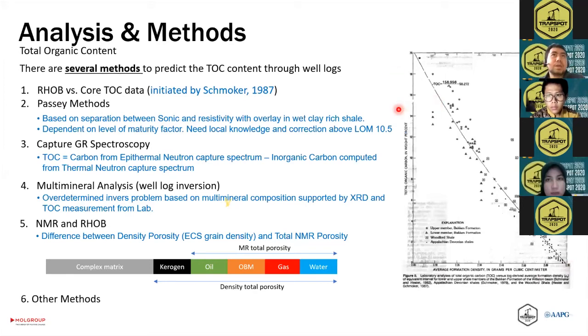Another one we can define is the Passey method, which is delta log R, based on the separation between the porosity logs, normally sonic logs, and the resistivity log. You do the overlay and define the wet clay rich shale, and after that you will see separations indicating the hydrocarbon or the kerogen contained in the rocks. But the problem is sometimes we need local knowledge of correction about LOM, which is level of maturity. Normally we can use the rule of thumb 10.5, but it has quite high uncertainty. You need the information from the geochemical analysis about that.